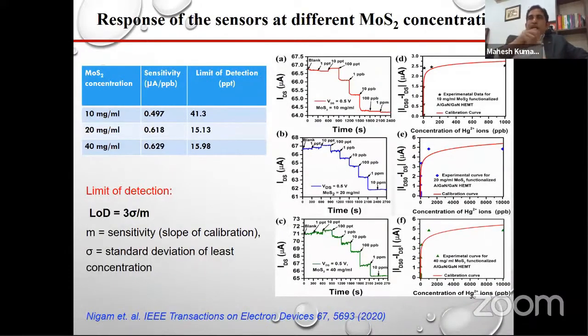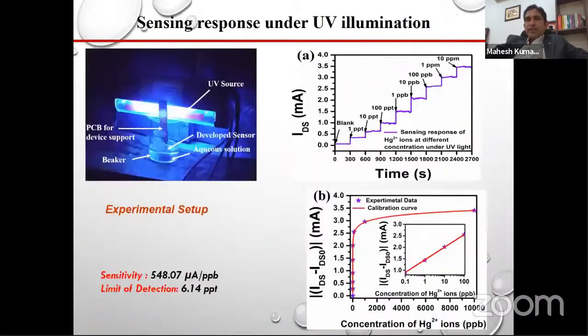Another thing, how much amount we have to load on the gate, that we have also optimized. We have taken 10 mg per milliliter, around 20 and 40, and we found the sensitivity is increasing, and the limit of detection initially decreased, then started increasing again. So the optimum is around 20 milligram per milliliter. We have to use this one.